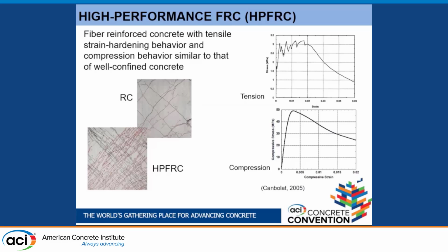The main attribute of these high performance FRCs is that if you take a sample made of this material, no reinforcing bars, just the fiber reinforced concrete, and subject it to direct tension, you're going to have, after first cracking, what we call a hardening or pseudo-strain hardening response. The top right figure is a plot of tensile stress versus average tensile strain. You see cracking, but then you have this hardening response. Once the capacity of the fibers bridging one particular crack is reached, you enter the softening branch of the response.